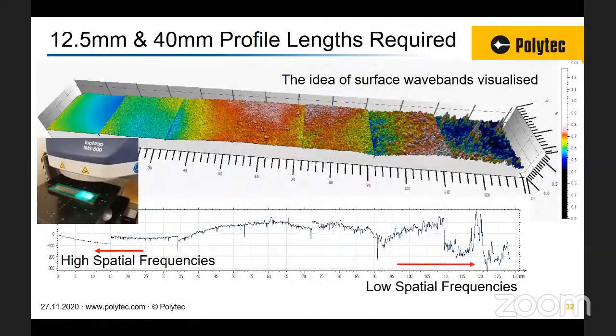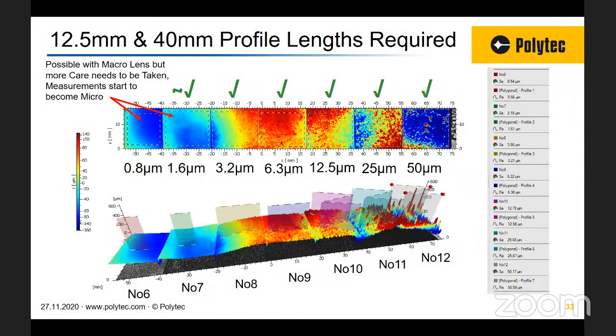Here I have a measurement of a roughness artifact, and this is interesting because it really shows the spatial frequencies and the relationship of spatial frequencies to high frequencies. As we go to the right, we've got lower spatial frequencies. As we go to the left, we've got higher spatial frequencies. And I've tried to demonstrate here where the macroscope is okay to measure. So the green ticks represent surface textures which are rougher. We need larger sampling areas to get stability of data as recommended by ISO. And of course, down at the higher spatial frequencies, you get to the crossover point. So when you're at 0.8, you can get a representation of texture, but you're really crossing over to microscope type systems then.